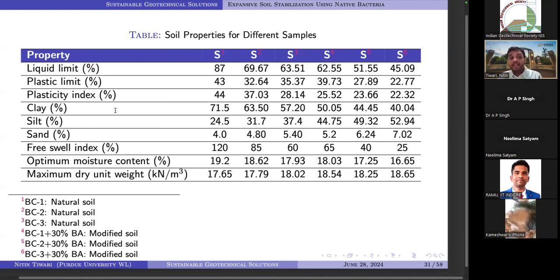We have also taken care of the free swell index. If you check, we have taken a wide range of the free swell index. With modification, it ranges from 25 to 120%. We have very low swelling pressure soil, and a very high one at 120, not too high, to be honest, but at least we have a wide range of the swelling index, so that we can see the treatment we are doing is really robust. Even the clay content ranges from 71% to almost 40% in the soil. These are very important parameters when doing this kind of research. It should be widely worked out. It should not be one area, one soil, and finish it. No, there should be a wide range of material we need to take and figure out.